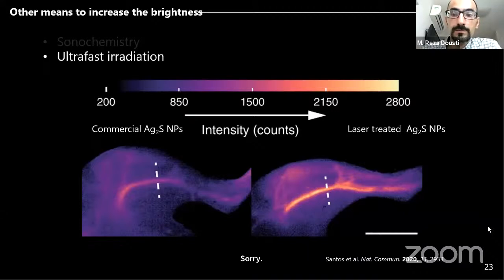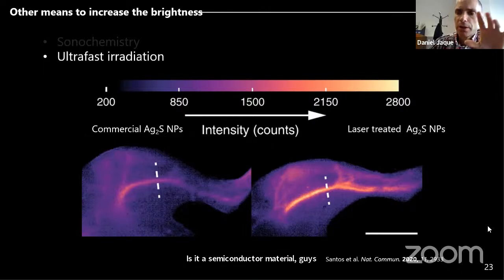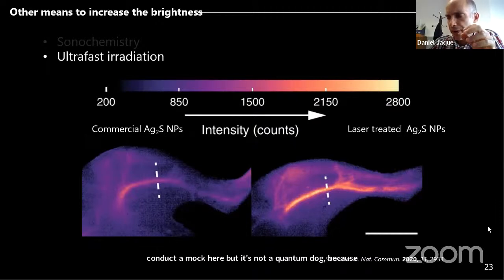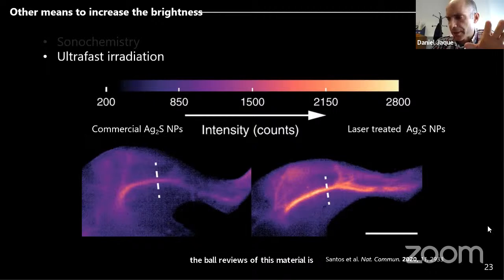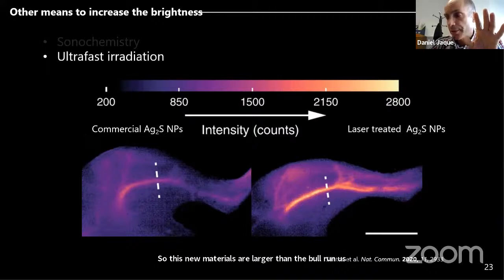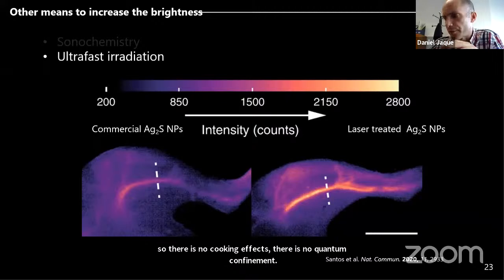Yeah, it's a semiconductor material, but it's not a quantum dot, because the size of these nanoparticles is 10 nanometers, and the Bohr radius of this material is 2 nanometers. So the particles are larger than the Bohr radius, so there are no quantum effects. There is no quantum confinement. So it's a semiconductor, yes, but there are no quantum effects in this material.